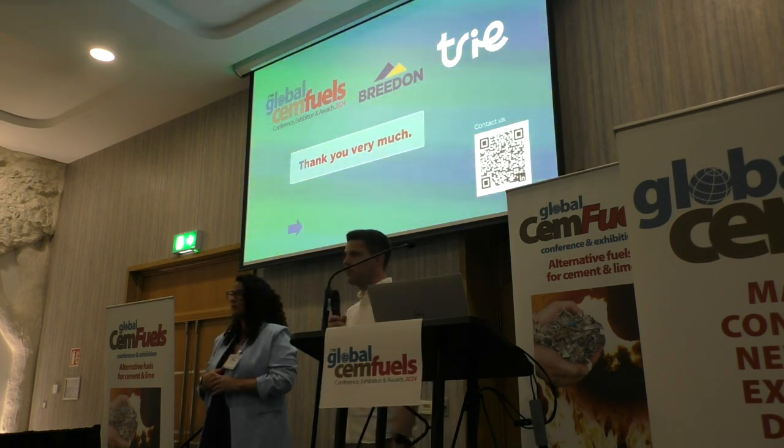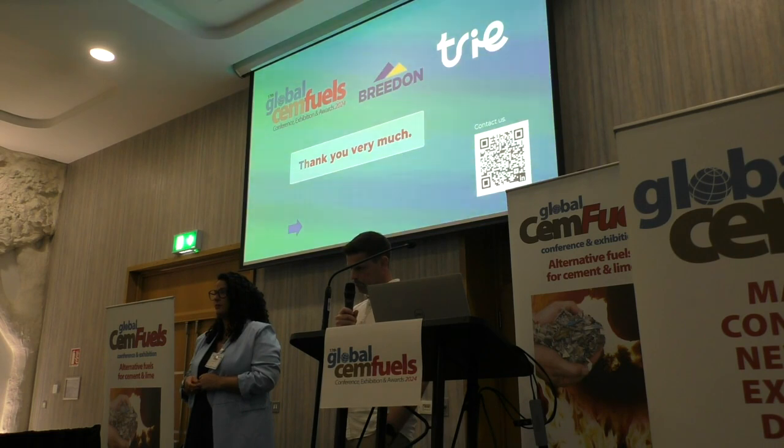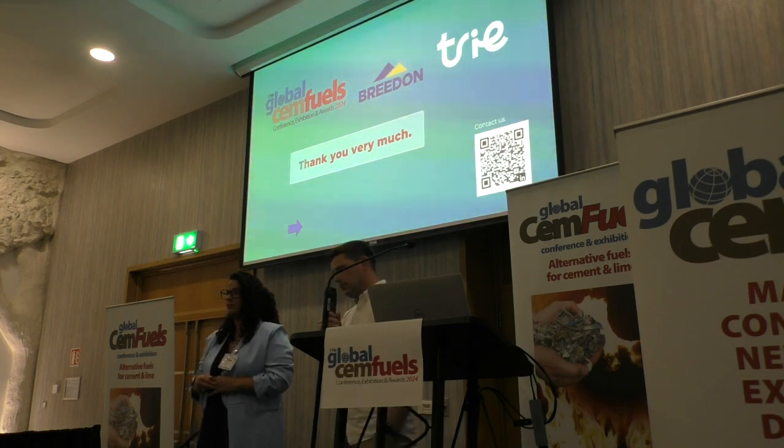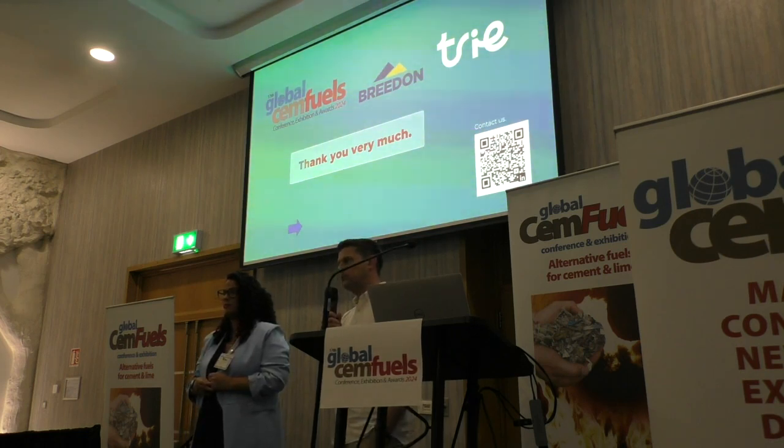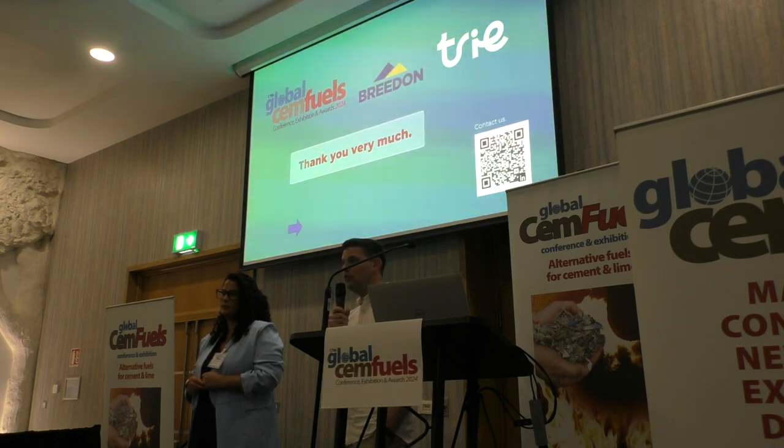Oh, sorry, just one additional question, if I may. Do you ever have the opportunity to analyse the composition of the kiln ball? So if it is disgorged from the kiln and passes into the cooler, is there any possibility of picking up pieces of the kiln ball and determining whether or not the composition of the kiln ball is actually any different from the clinker itself? Yes, we have, and we have analysed that in the past, and it is very much different. It's a lot more unburnt. Free lime levels will be higher. You will have a lower sulfur content. There have been several analyses on it also. Yes, that's correct. Okay, that's great.